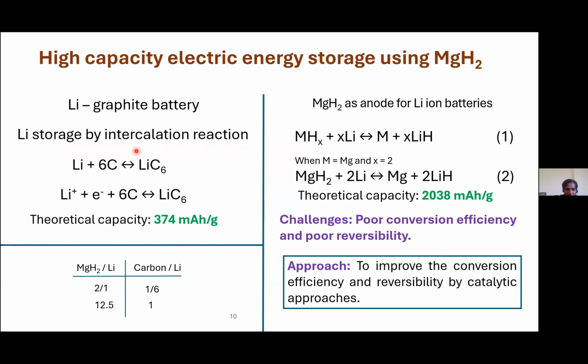Here, the lithium-ion battery reaction, I said in the first slide or the second or third slide itself. Graphite as an anode active material provides a capacity of 374 milliampere hours per gram, and magnesium hydride in that place does 2038 milliampere hours per gram. Oh, then if it is great, why don't you use it? If something is promising, then why don't we use it? There are challenges. When nature provides you something amazing like this, it also provides some challenges that we have to come across and solve.